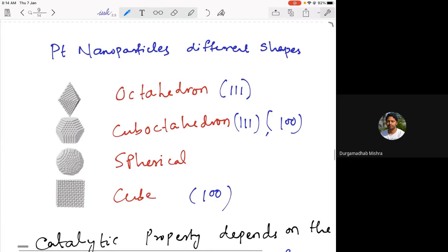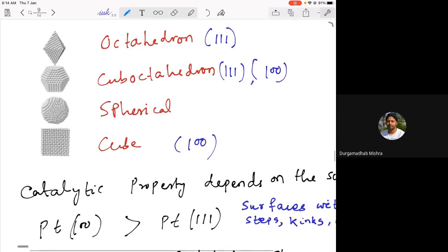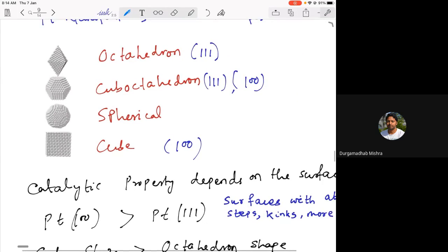So as you can see, different shapes have different surfaces which are exposed and which can be used for catalysis. And what was actually observed is that if you look at the platinum 100 substrate, like in the case of the cube, you have the 100 surface which is exposed. That surface has much better catalytic properties than the 111 surface.